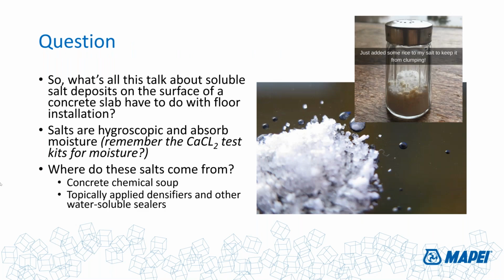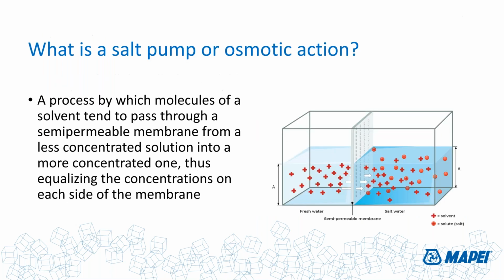So what's so bad about that? Well, as we mentioned, these salt solutions are hygroscopic. And when they come in contact with vapor or moisture, they're going to solvate, and they're going to create a higher concentration of solution on a very low concentration of solution below it. So I'm sorry, I'm going to try to explain this again. If I have a high concentration of salt on the concrete surface,